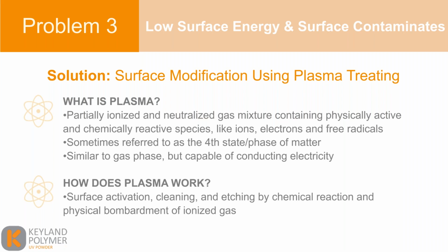Thank you, Evan. So yes, now we'll talk about the third problem, or the third part of this stool, that is coating heat-sensitive and non-conductive materials. It's low surface energy. As we know, many of these composites and materials have low surface energy and surface contaminants by their nature. One of the ways that we get around adjusting the surface energy and removing these contaminants is plasma treating. Similar to a metal finish where there might be a multi-stage wash, plasma has similar attributes. So it's going to remove some surface contamination, and it's also going to prepare the surface by changing it to be more receptive to a coating.